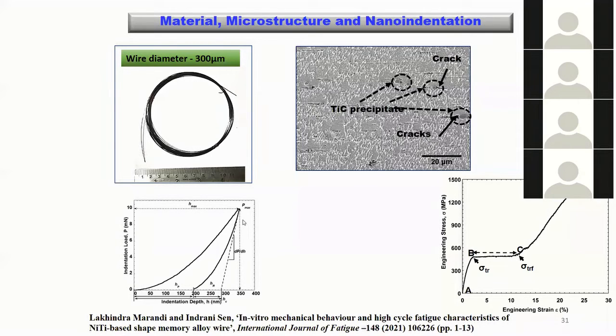We did the typical indentation behavior at the very first instance to evaluate the mechanical properties of the material for the localized volume. And we see that it gives us a hardness and elastic modulus which is quite similar to what is expected for this material. Okay, the elastic modulus is something around 60 GPa, which is what is expected for this material in the austenite phase.